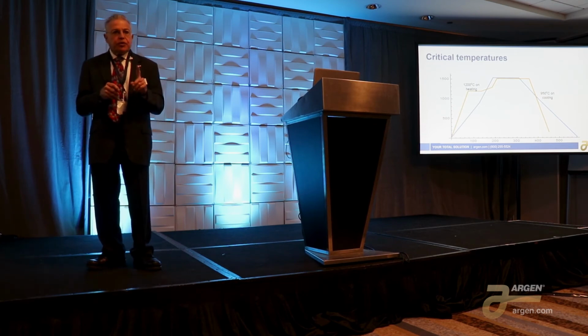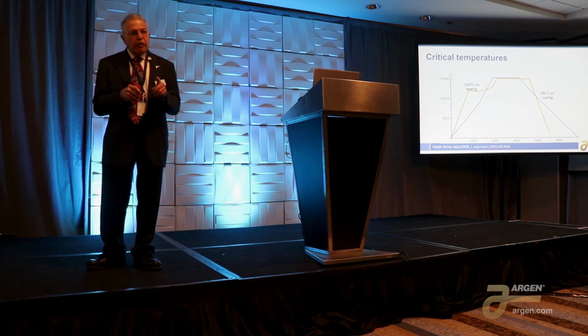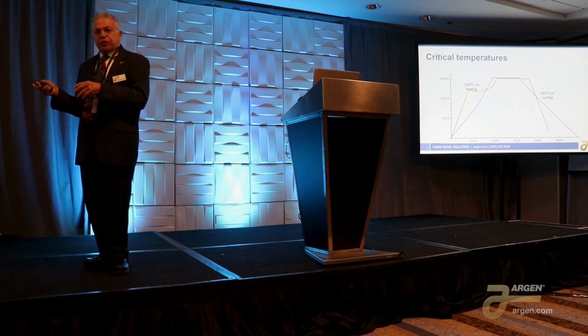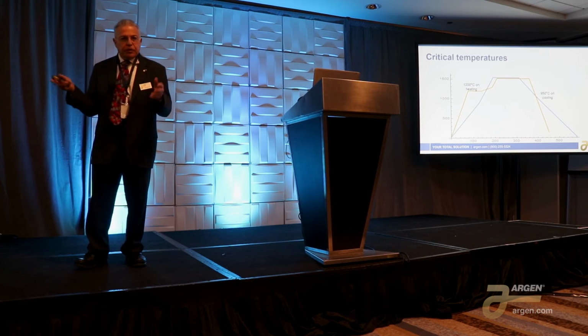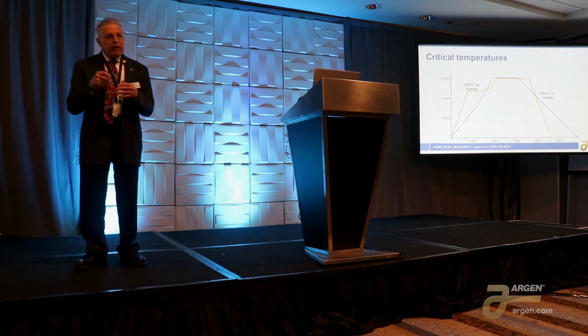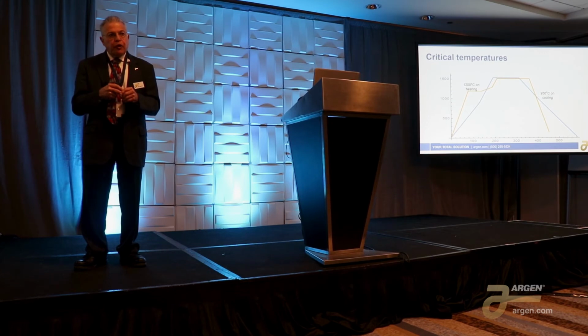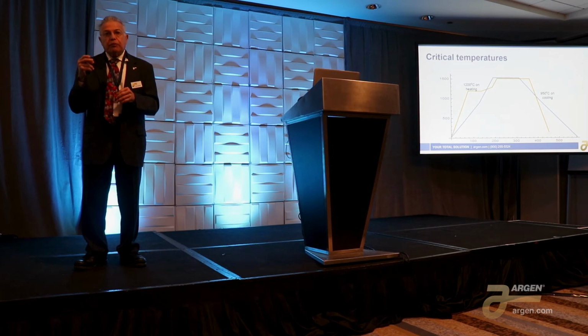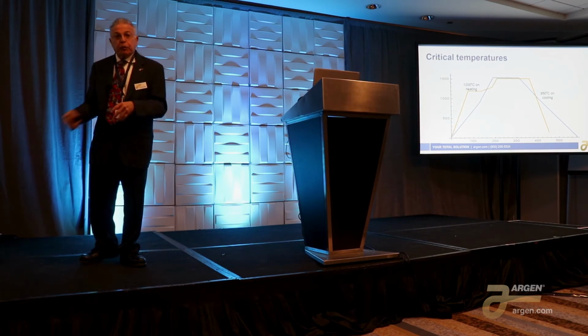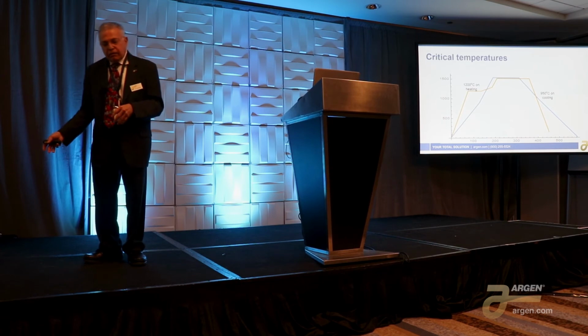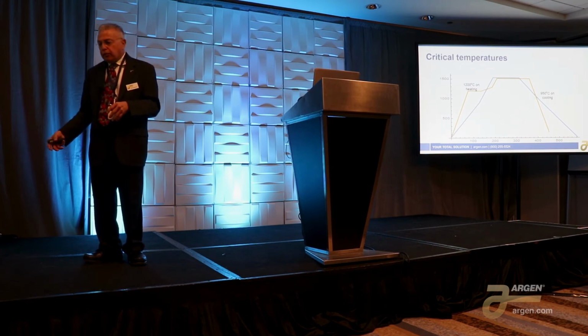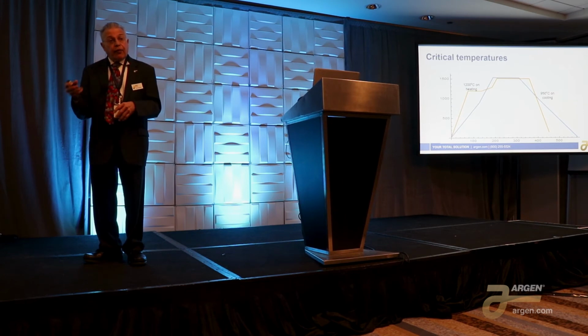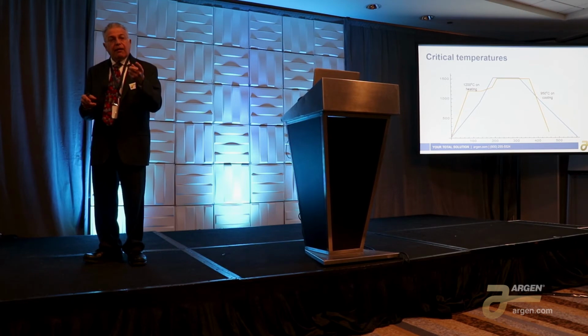So people started creeping up the temperature a little bit. That's not true with the newer zirconias. With the newer zirconias, whether they be the super translucent or the medium super translucent, the HT plus, you can't vary the sintering temperature too far away from the manufacturer's recommendations. If you do, the material will start to become opaque. So if you took a super translucent zirconia, whether it's Argen or BruxZir, doesn't make any difference, and fired that at the same temperature you were firing your high translucent material, it would be opaque. It wouldn't have 50% translucency.